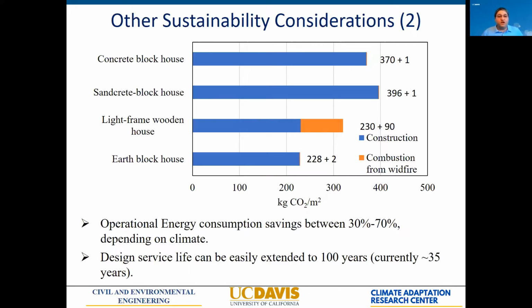Also, in terms of operational energy consumption, you can get very significant savings using earthen construction, between 30 and 70%, depending on the climate. And another advantage that is often not considered is that the design service life of these houses can be much longer than that of other houses. There are examples of houses that easily live to 100 years, while current wooden houses have a theoretical design life of 50 years, but an effective design life of about 35 years.